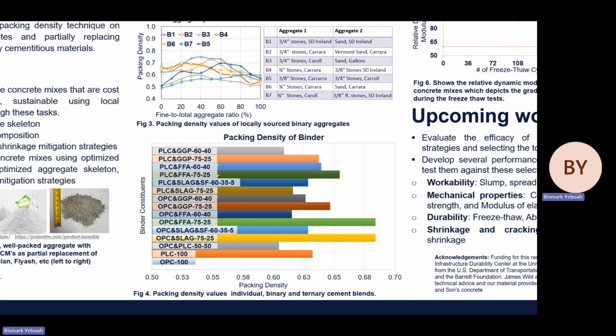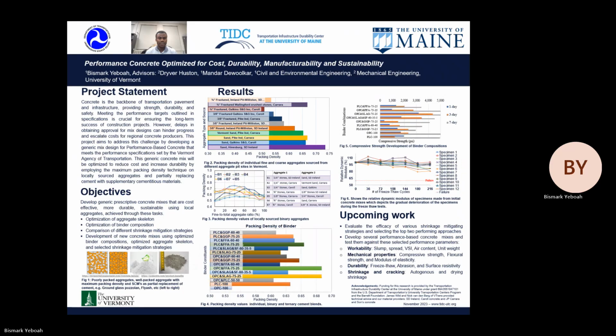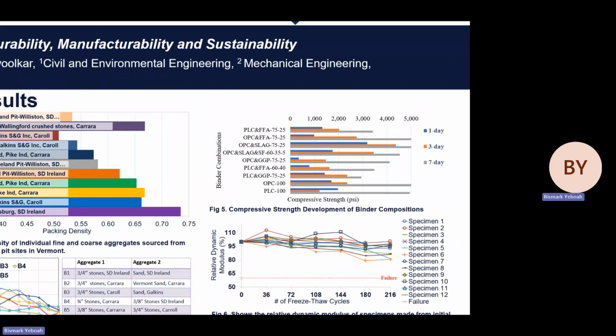Tests were also conducted to determine which combinations of the cementitious materials attain higher compressive strength. From figure 5, we can see this test. This test was undertaken in accordance with ASTM C109, which requires making 2-inch cube specimens of the cement mortar for the different cement combinations and crushing them on the first, third, and seventh day. It can be seen from the test results that 75% OPC and 25% Class F fly ash, and 75% PLC with 25% Class F fly ash, had the maximum compressive strength of about 5,000 psi.